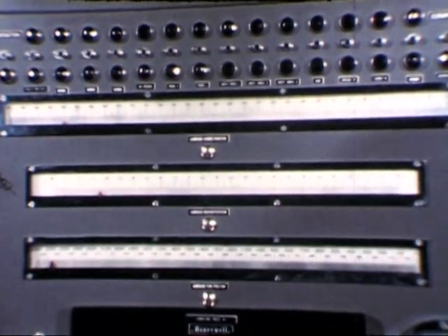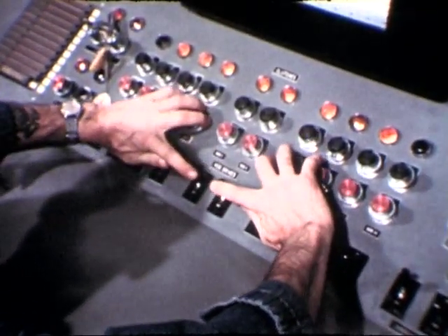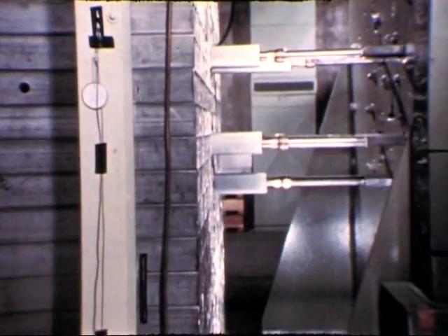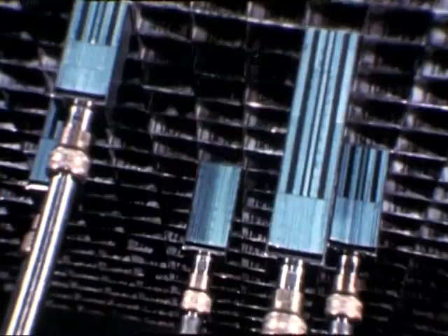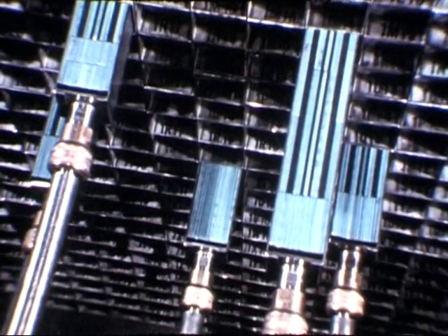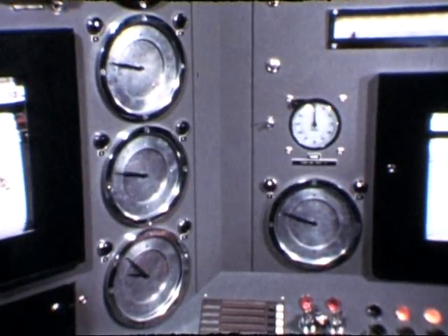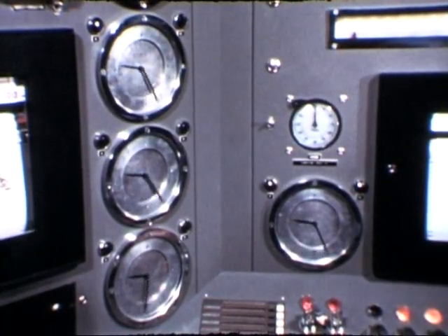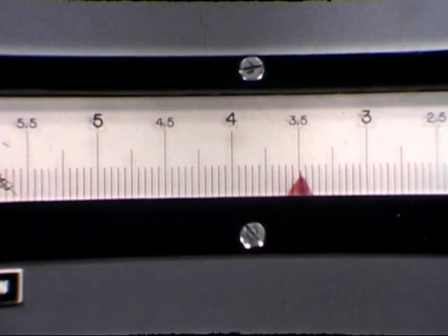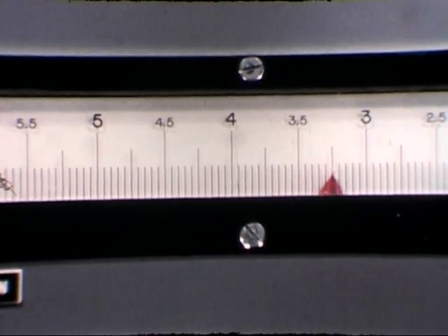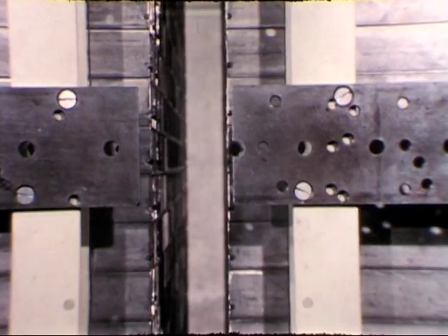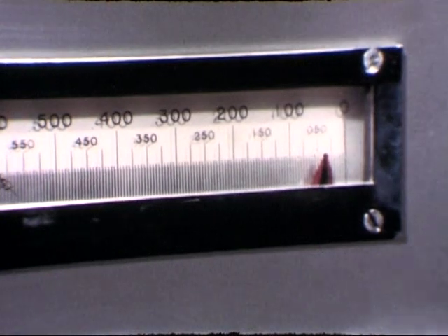At the same time, 4 safety rods in each half are inserted. These 8 rods must be fully inserted before the separation can become less than 18 inches. 1 rod in each half is a control rod and is left withdrawn until the halves have been completely closed. As the separation of the halves decreases from 18 inches to 3 inches, the speed is reduced to 6 inches per minute, and the final closing is at a rate of 1/2 inch per minute. The slow speed of assembly is fundamental to the safe operation of this machine.